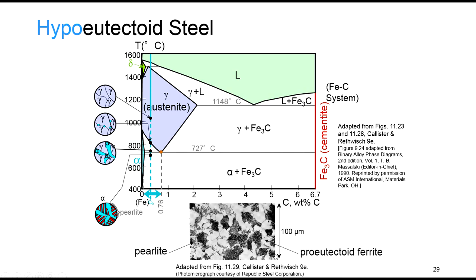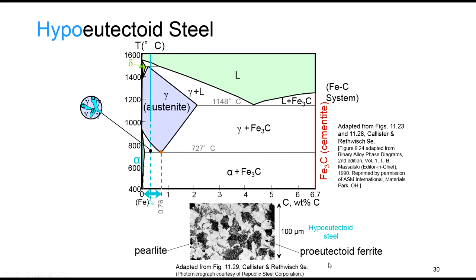And this is what's shown in the microstructure of the same system under microscope, which is showing pearlite structure and pro-eutectoid ferrite. To find the weight ratio, of course, we can use the tie line as shown here. The weight ratio of alpha phase is S divided by the total value, and the weight ratio of gamma phase here is 1 minus W alpha.